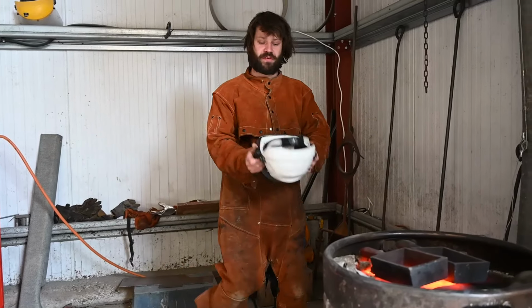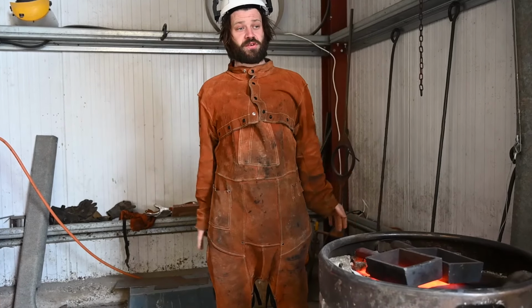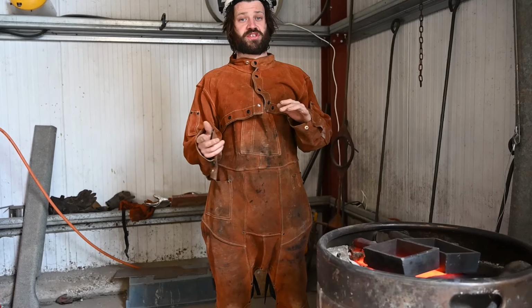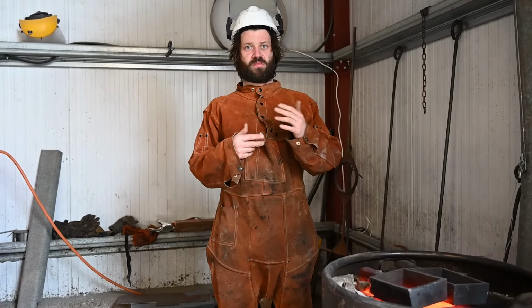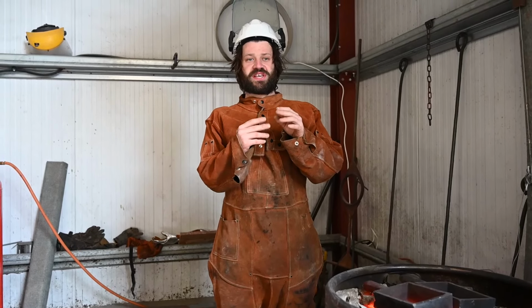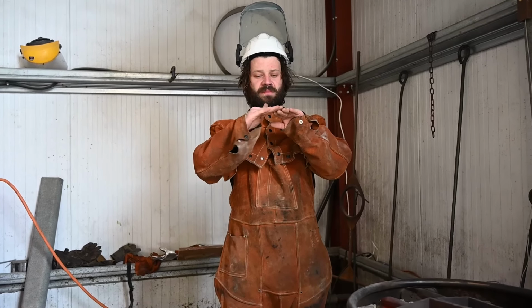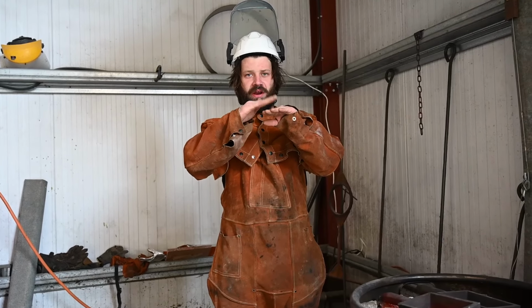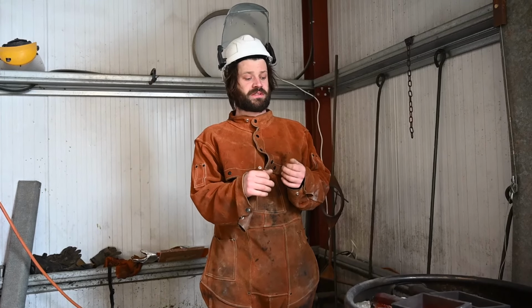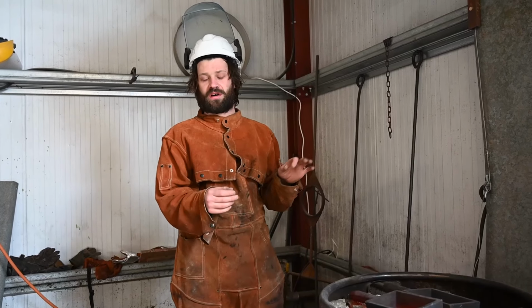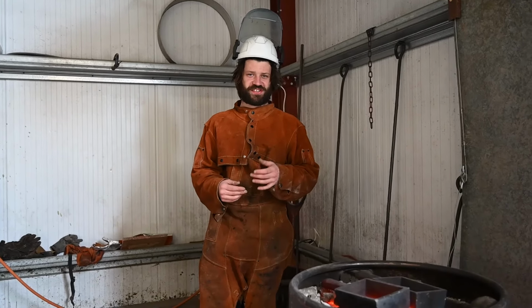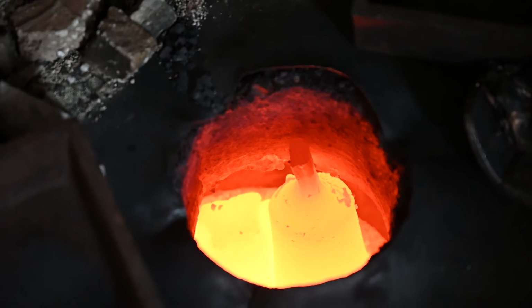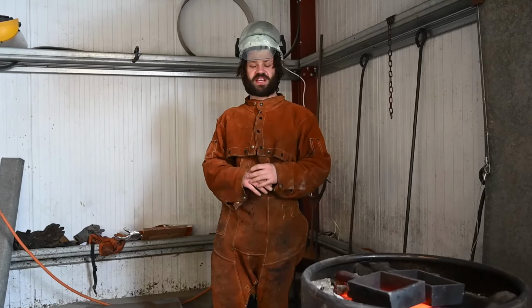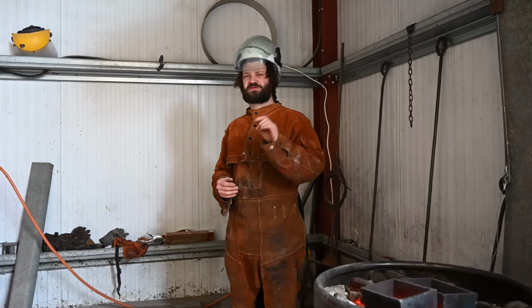We don't want the bronze overcooking. If you overcook the metal, from experience, when pouring into shells, the bronze bubbles more than it should. The gas is trapped between the layer of bronze and the ceramic shell, and it bubbles away. Once it's solidified, you end up with a really pitted surface on your metal. So the key is not to have it too hot. Obviously 1100 degrees is very hot, but any hotter, 12, 13, 14, it can cause some surface issues.